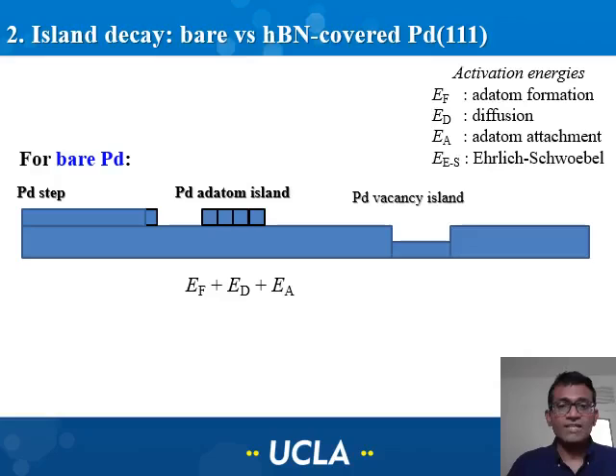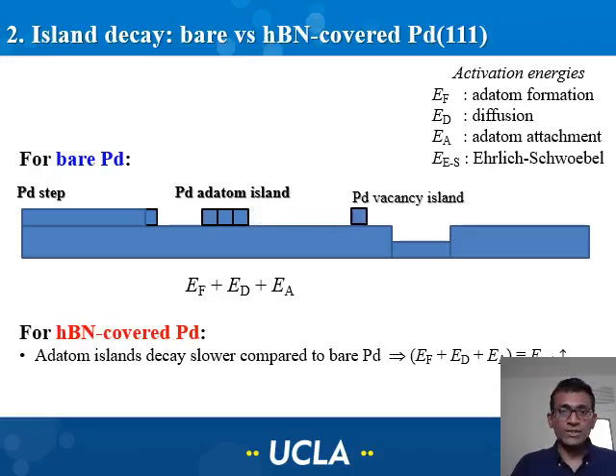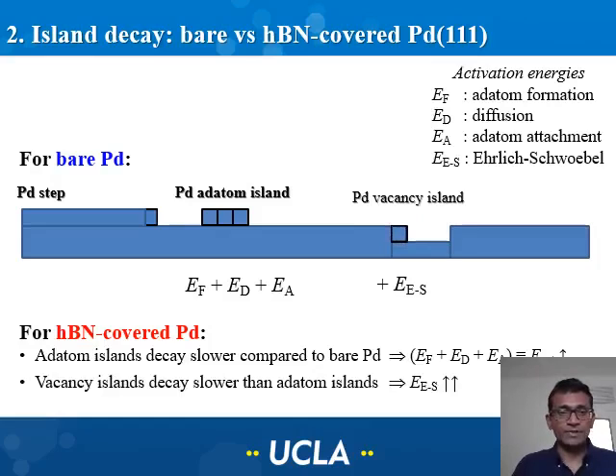And if a vacancy island is supposed to decay, then it requires filling up this vacancy island with atoms jumping across these step edges, which can have an Ehrlich-Schwoebel barrier associated with this process. And it turns out for bare palladium, you have all these energies and the Ehrlich-Schwoebel barrier that influence the rates of decay of atom islands and vacancy islands. It turns out that when you have hexagonal boron nitride covered palladium, all these activation barriers are significantly increased. Okay, my time is running.